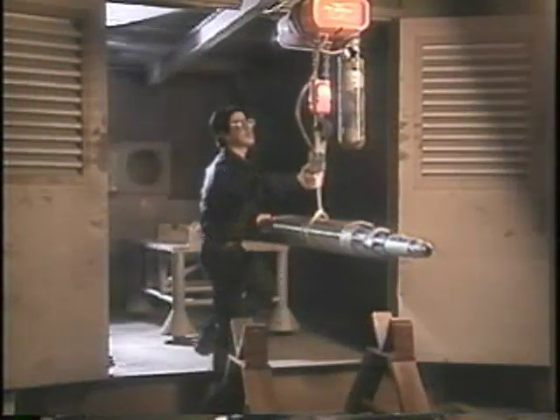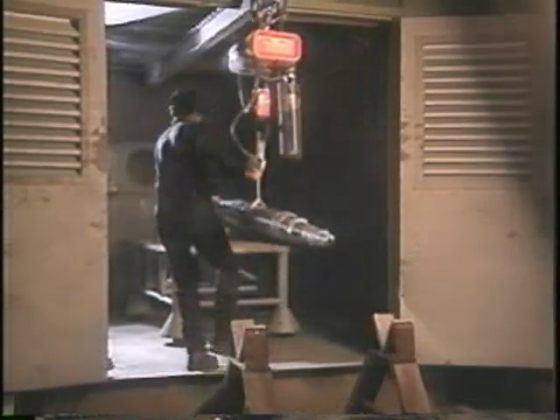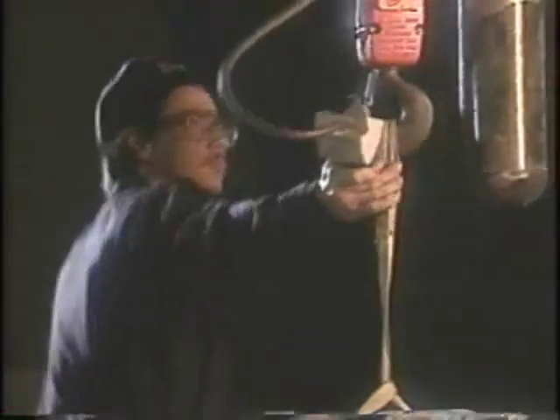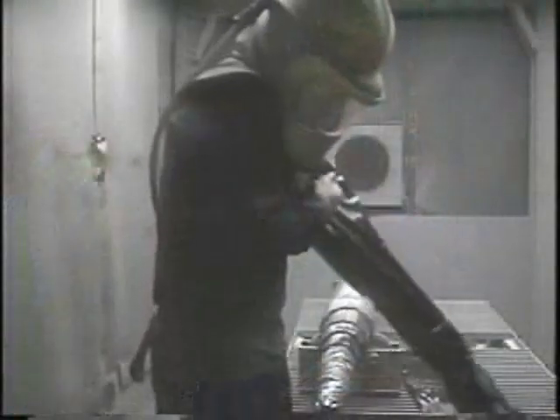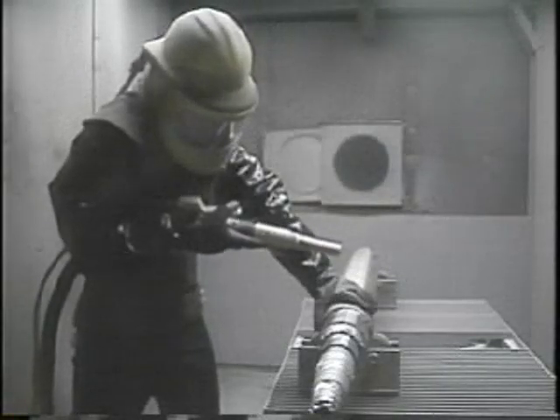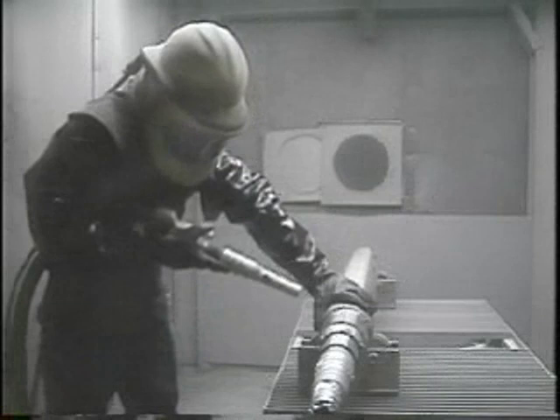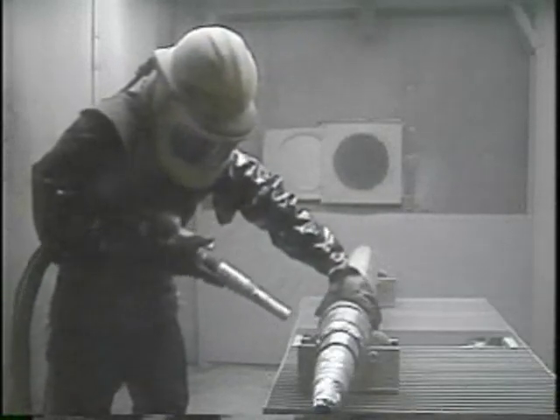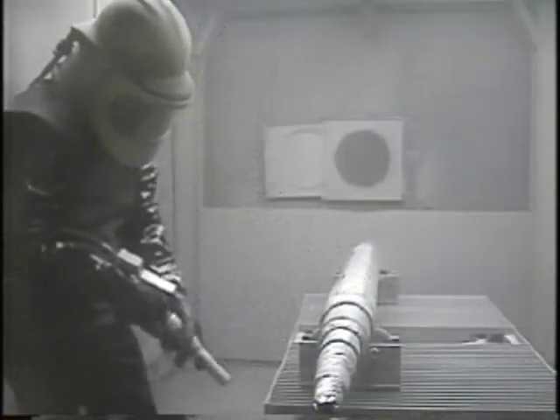To give the tungsten carbide a good surface to bond with, the part is grit blasted with aluminum oxide. Different grit sizes and air pressures are used to create the various surface finishes required. For thicknesses up to 5/1000ths of an inch, the surface is finished to 100 to 150 RMS. If the coating will be more than 5/1000ths thick, the surface finish will be 200 to 350 RMS. A clean metal finish is absolutely essential for maximum coating bond strength. Time is important. Since rust can attack unprotected steel very quickly, the part is coated within 1 hour of grit blasting. This one is now ready.